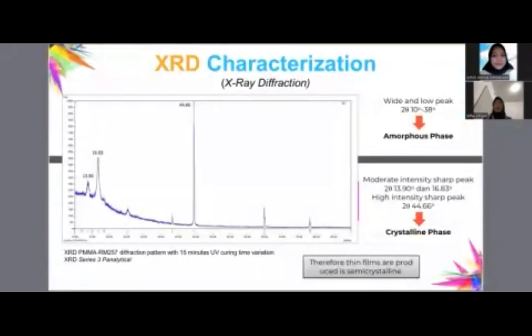Next, XRD. The sample characterized by XRD is the thin film with a UV curing time of 15 minutes. The sample was chosen because it has the best SEM result. Measurements are made at an angle range of 10 to 90 degrees. Based on the picture above, there is a shift in the diffraction pattern and an increase in intensity. There are wide peaks in the angle range of 10 to 38, indicating the amorphous phase. Sharp peaks with moderate intensity appear at 13.90 and 16.83. Then a sharp peak with high intensity appears at 44.66, which indicates the crystalline phase. Therefore, the resulting thin film is semi-crystalline.